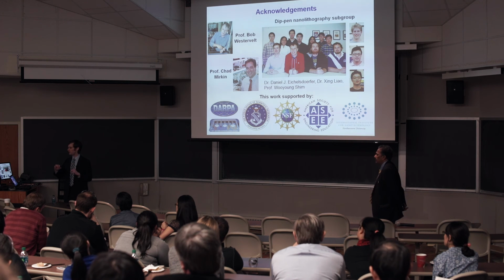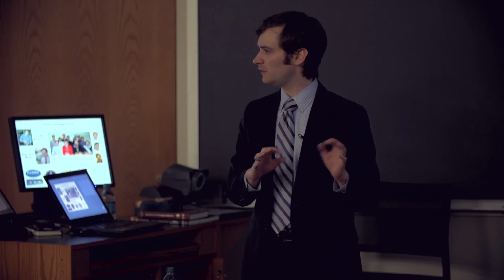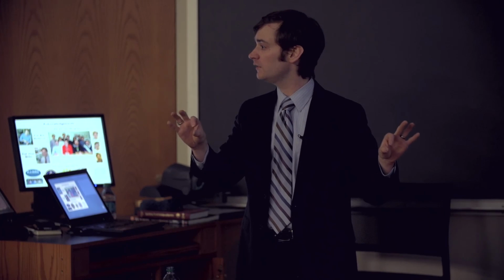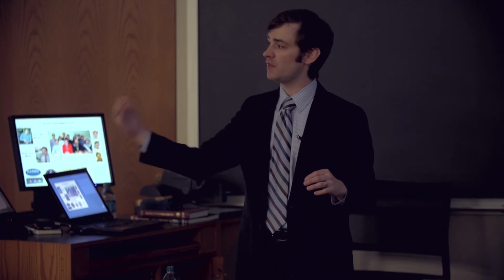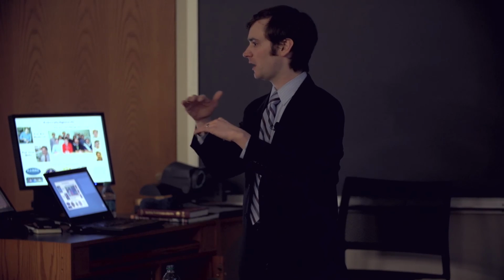And then, if there's any sort of residual heating and stress in the molding process. And so what we found is that in creating sort of 200 nanometer wide lines, that registry is good enough for that kind of capability. If you want to go beyond that, I imagine you'll have to do some kind of error correction, where you'll have to understand how they deviate from their ideal position and then correct that, which of course you can do by simply, if your writing patterns are every 100 nanometers, you can just sort of shift where it's going to be.